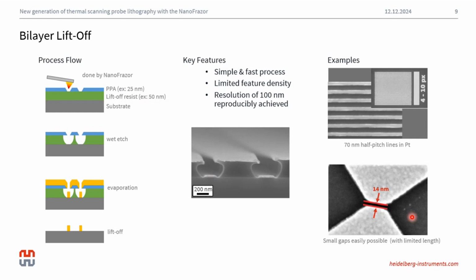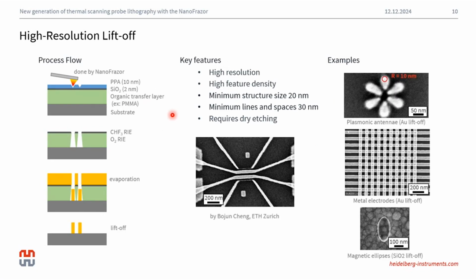And because we're not using a charged beam, we actually operate in a damage-free way using the heatable tip, and we found that with this heatable tip method, we can get much better electrical transport on sensitive materials than with E-beam. And I'll also show you an example of this later on. Now, going back to our liftoff, if we wanted to push the resolution further with the liftoff method, we can do so as well. We just need to modify the resist stack slightly here. In this case, we also need to use a dry etching pattern transfer method so as to maintain the integrity of the features written in the top PPA layer.